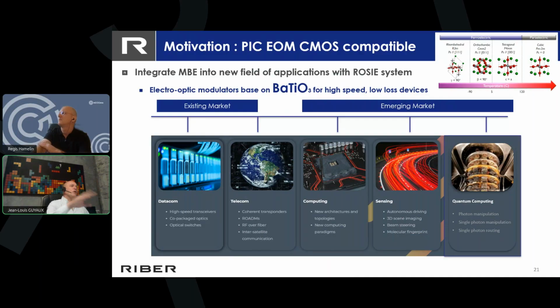Tetragonal means that in the cubic phase, you have the central atom, which is a titanium atom. When it becomes tetragonal, the titanium moves up or down or aside, building a permanent electric field. This phenomenon, the tetragonal phase, makes this material ferroelectric, with these remarkable properties. Thus the job of the machine and of the growth is to force the material to become tetragonal with the proper orientation. I told you that you can move the titanium atom from the top to the bottom, which means you will have a polarization perpendicular to the substrate. This is one phase. But for the PIC industry, you also need to have the electric field in the plane, and this is mainly the management of the stress during the growth.